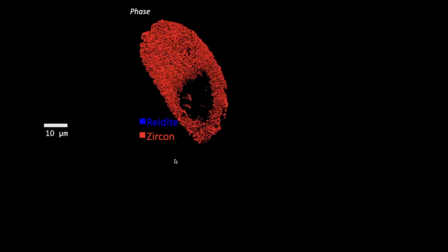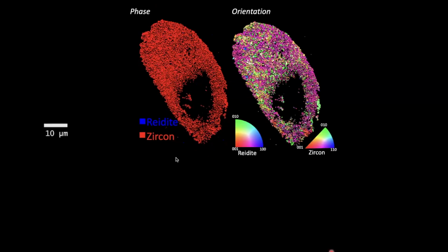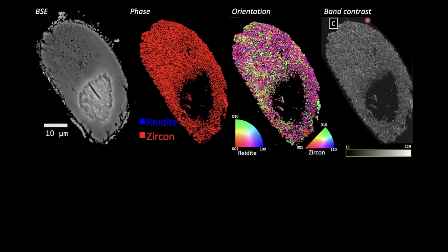So EBSD gives you a phase map. So this was basically all mapped as zircon. I think there were some little individual Reidite pixels in there that I didn't remove because I didn't want to lie about them being there. But when it's just one pixel, it's hard to tell if that's real or not. It also gives you an orientation map where the colors are different orientations for Reidite and zircon. And then it gives you band contrast, which is kind of how good the indexing of the patterns was. And then I also put the backscatter electron image that I showed earlier side by side just for comparison.